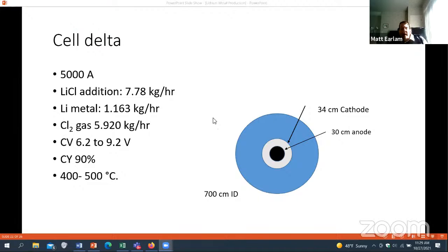So here's what a cell actually looks like in terms of sizes. You have here in this example, which is a German cell, not the ones in North Carolina, the anode about 1 foot in diameter, and then the cathode about 34 centimeters in diameter. So the gap is about 2 inches. And then the total bath around this cell was 700 centimeters, so pretty big. They operate at about 6 to 9 volts. The current yields are about 90%, which is pretty good